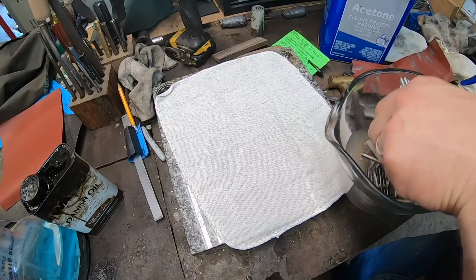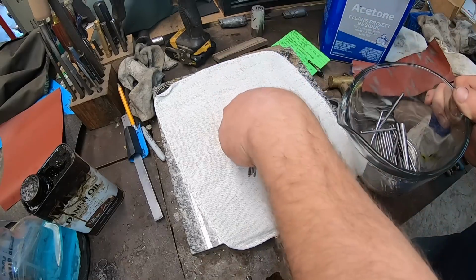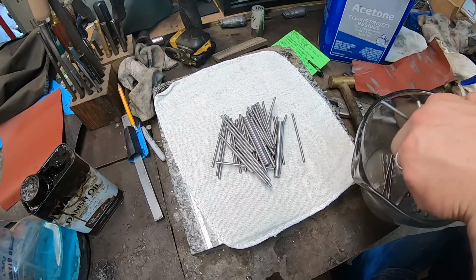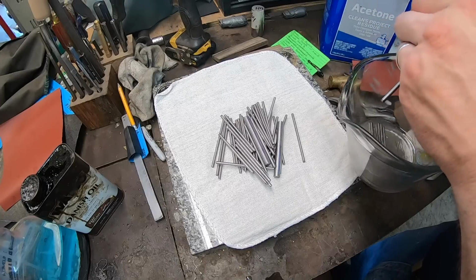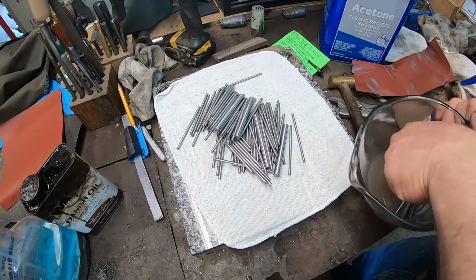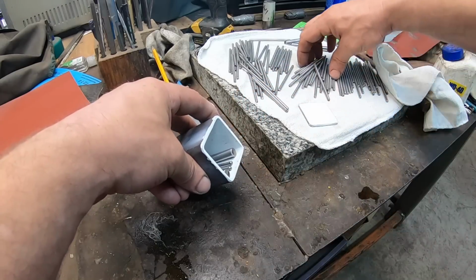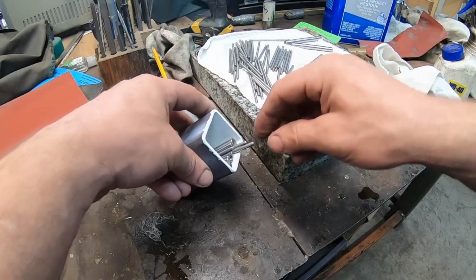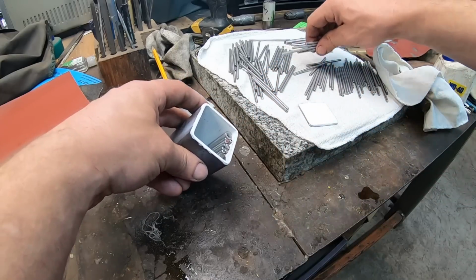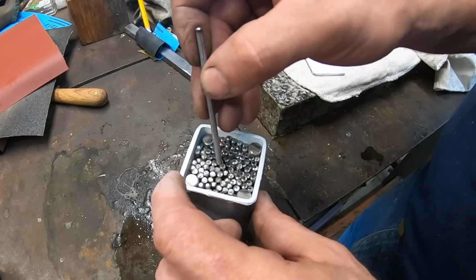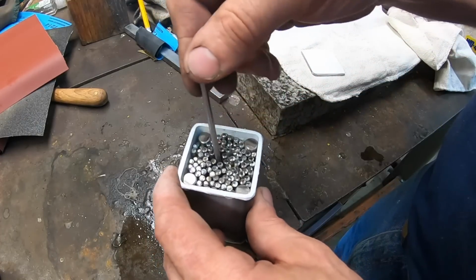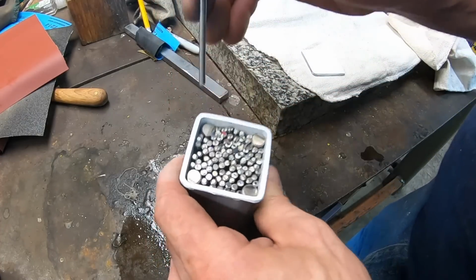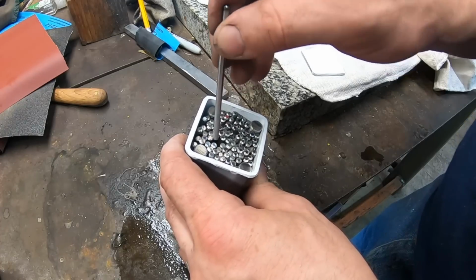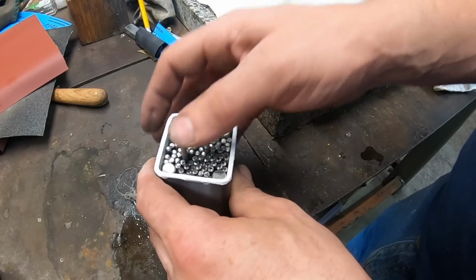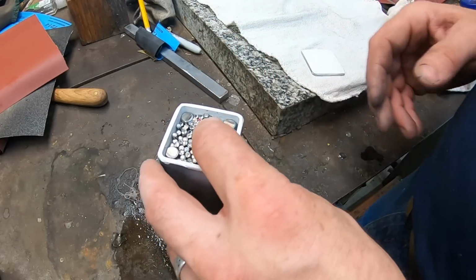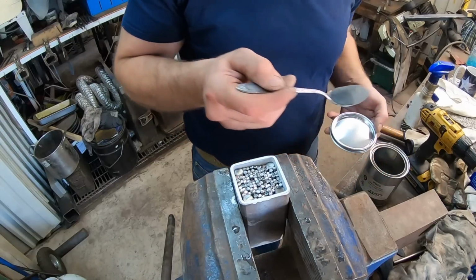Now you'll notice some larger rods in there. That's 3/8 inch O1 tool steel rods, and the only reason I had those was for additional space filler in the canister. I did not purchase quite enough of this 3/16, or is it 5/32? I don't remember. I think it's 3/16 inch rod. And so to fill the canister up, I put 4 pieces of this 3/8 O1 in the corners, and we got a pretty decent fill up there.